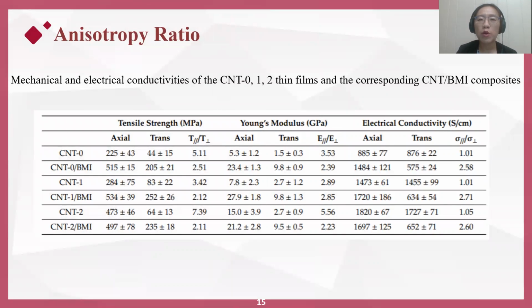Here is a table summarizing the mechanical and electrical properties. Interestingly, both the mechanical and electrical properties of the CNT composites exhibited a consistent anisotropic ratio around 3, which is presumably an indicator of the stretching-induced CNT alignment.